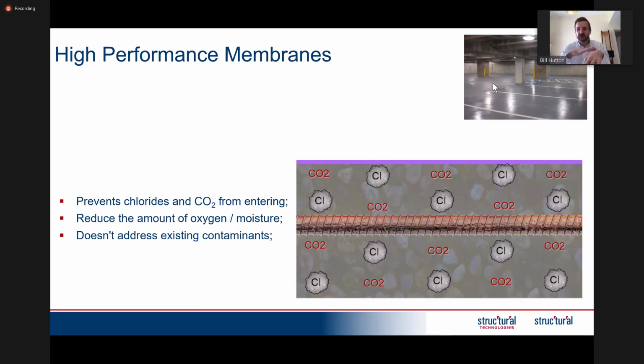So even if you put a high performance membrane on it, it can do two things. For an elevated slab, it will prevent oxygen from getting in, so that would slow down corrosion. If you have a slab on grade, then the membrane will prevent moisture from evaporating. That means the slab will become more saturated, which again will reduce the availability of oxygen, so it will reduce the rate of corrosion. So membranes can be used to kick the can down the road, if you like. They can be used as short-term solutions to reduce corrosion, but not necessarily mitigate corrosion.